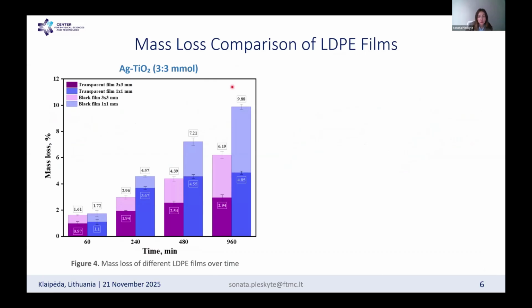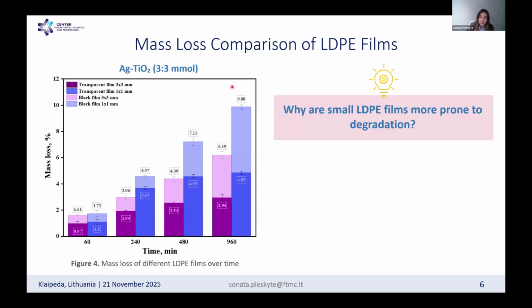We noticed that the higher degradation efficiency was found for smaller LDPE films, which had a size of 1 by 1 millimeter, compared to the larger LDPE films. And of course, very naturally, there is a question: why are smaller LDPE films more prone to degradation? This could be attributed to the fact that smaller LDPE films have a higher surface area to volume ratio than larger ones.